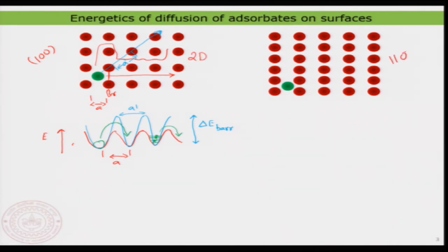But now when it comes to the 110 surface, there is something interesting here. Of course, the atom is again sitting at the so-called twofold hollow site, that's the most favorable site, this is all clear. But you see that when it needs to move along this particular path, the barrier that the atom is going to feel is relatively very, very less. It is going to be quite shallow compared to an atom which is moving along this path, because you can see that the atom needs to literally climb up. So again the barrier is going to be very, very high. This is the reason why you get a very preferred direction in the diffusion on the 110 surface. And that is also the reason why you have seen that the diffusion on the 110 surface is more one-dimensional than two-dimensional.